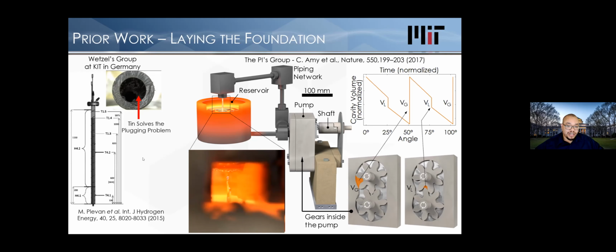And so our main contribution is that we have this infrastructure. We can make an all graphite infrastructure or an all ceramic infrastructure, and we can pump the liquid tin. So we have no corrosion, right? So no corrosion whatsoever at any time scale. And we can go much hotter. So we can go to 1400 degrees C or hotter if we needed to. 1400 degrees C is about where this reaction goes to completion, where you'll get pure hydrogen, 99.99% pure hydrogen.